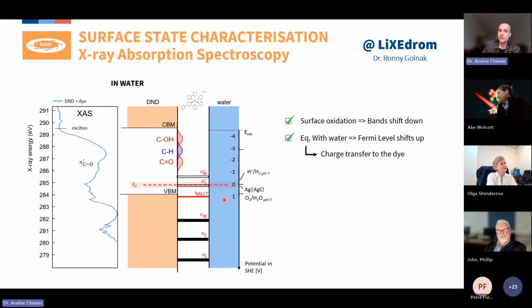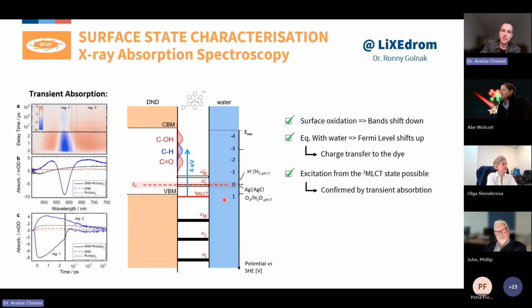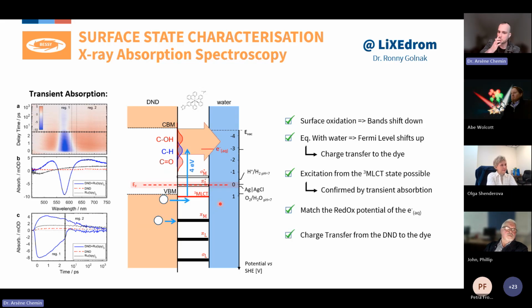So just because we equilibrate with the liquid, we charge the ligand, and this state that was previously unoccupied can then be photoexcited. Another proof of this photoexcitation was also given by transient absorption that was observed in liquid and can only be explained if this 3MLCT state is populated. And if this 3MLCT state is populated, then we can have the photoexcitation of the diamond. So this is how, through X-ray absorption spectroscopy and some other techniques like transient absorption, we were able to understand that it's the equilibrium of charges in the liquid environment that provides charges to the ligand and enables the excitation in the visible range, and the emission of solvated electrons.